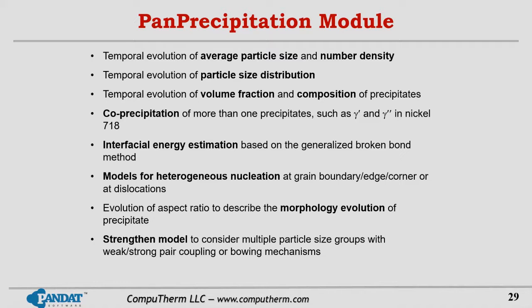We can use the module to estimate interfacial energy, and we can consider heterogeneous nucleation. We can also consider different morphology evolution, it's not limited to spherical. And the new version of 2019 also includes some strength models for nickel-based superalloys.